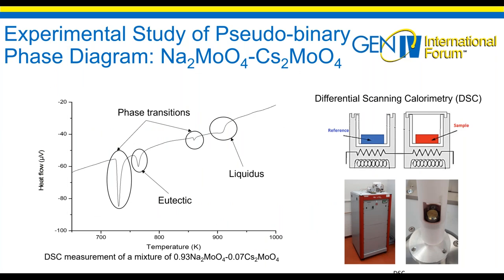And to get the phase diagram data, we used differential scanning calorimetry measurements. So basically, you put your sample here with a reference here, and you heat them at the same time, at the same temperature. Here you have a picture in a more real way. If something is happening to your sample, like phase transitions, eutectic or liquidus transitions, you will release energy. And this energy, you will see it here on the heat flow measurements, where you will have a peak like this, for example. So this is a typical DSC measurement of a mixture of Na2MoO4, Cs2MoO4 in this ratio. And you can see that you have two phase transitions, one eutectic and one liquidus here.